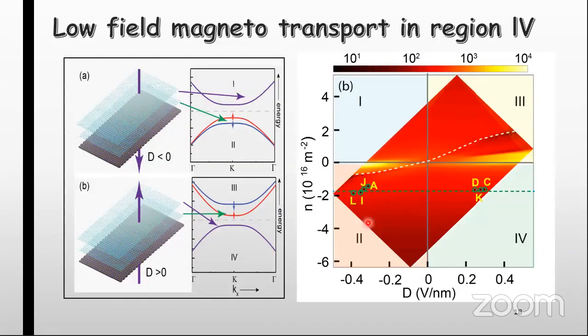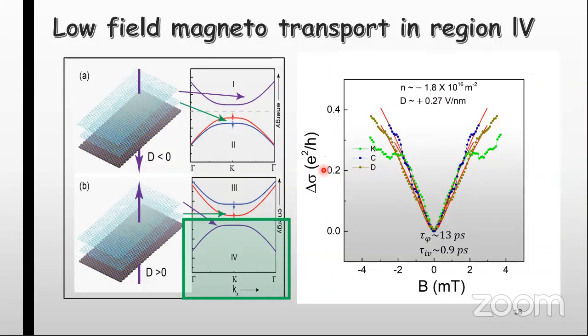To further do a quantitative analysis, we did a low field magnetotransport measurement. We chose a constant number density line, this green line, and along this we performed the magnetoconductance measurement. First we chose quadrant 4, where there is no spin orbit coupling in the valence band, and we found that it is showing weak localization behavior. This is what we expect in intrinsic bilayer graphene, because it also has a weak spin orbit coupling. These red curves are the fits to this experimental data using the theoretical equation. These are the parameters we got after fitting: the inter-valley scattering time was 0.9 picosecond, and the phase decoherence time was 13 picosecond.